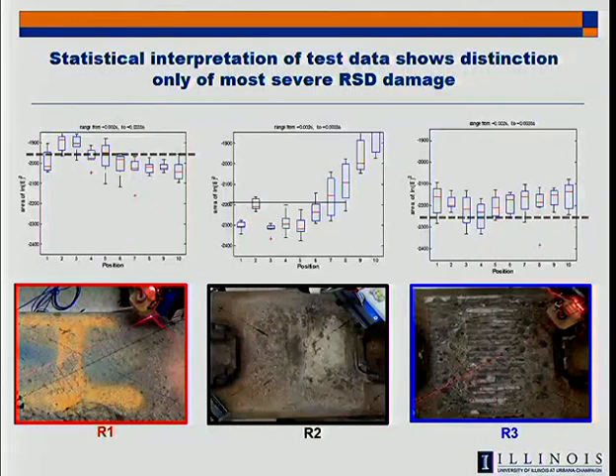Aha, the energy that we measure is lower here because of the scattering than here. But the moderate case of RSD, we have both in the range of good and in the range of bad. So I was expecting that we would have 3 horizontal lines, one high, one medium, and one low. We did have that for the extreme cases, but in the intermediate cases, it looked like we have some regions that are bad and some regions that are good. So we couldn't say whether it's definitely good or bad, but we could say that not all of it is good. So in a way, we are saying that it's intermediate.